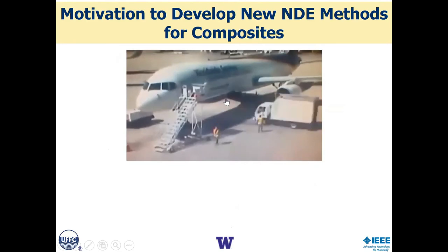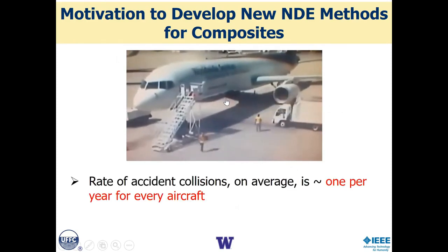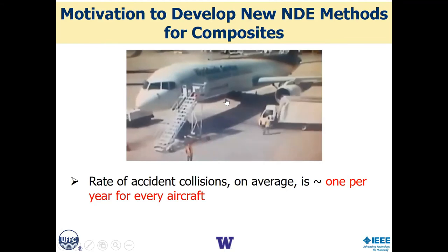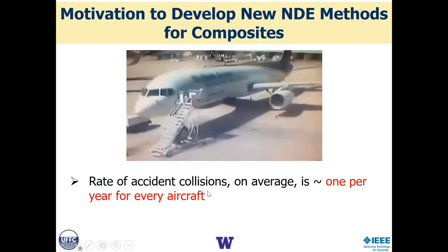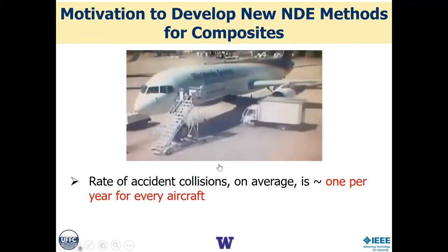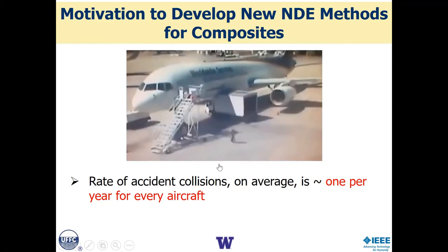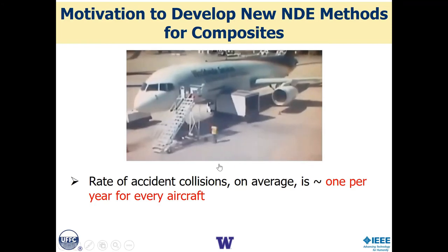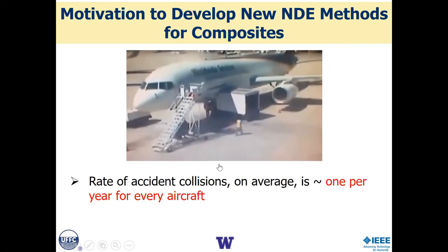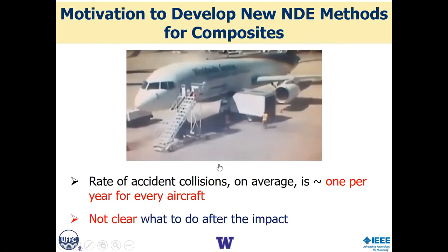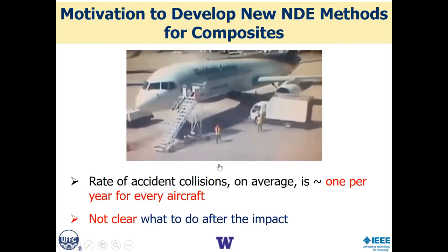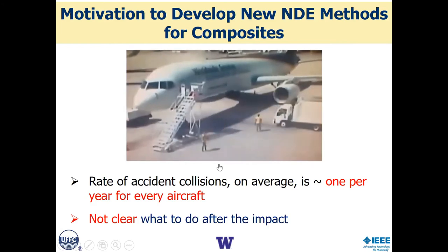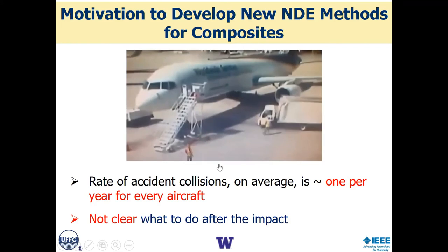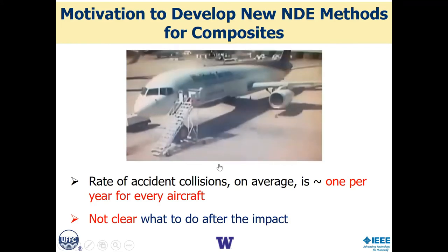You laugh a little bit, but we found out from our friends at Boeing, because Boeing commercial aircraft is headquartered in Seattle, that this happens on average once per year for every aircraft in the worldwide fleet. Not that a truck runs away, but some kind of vehicle impact, lightning strike, or bird strikes, either landing or taking off. For metal aircraft, it's very clear what to do, because you can visually inspect the surface, and there's a very strong correlation between the visual surface damage and the volumetric damage to the aircraft.